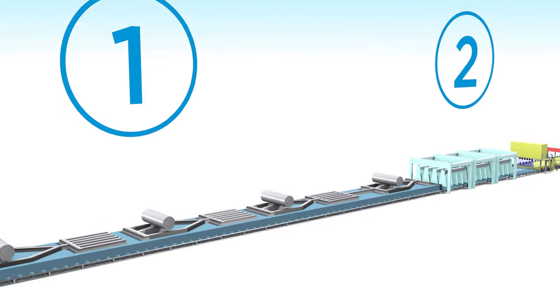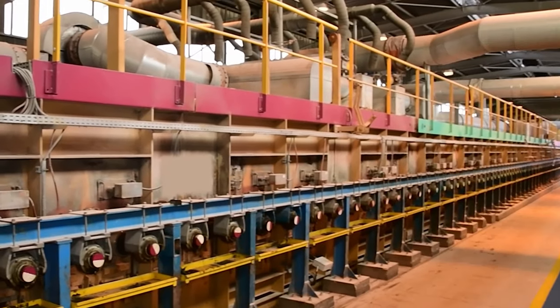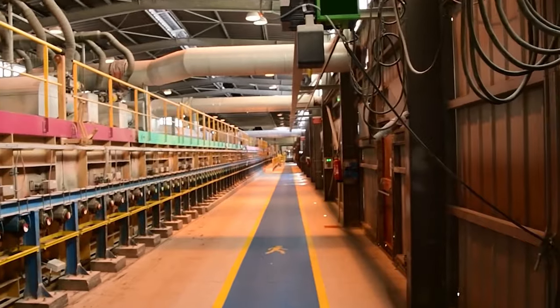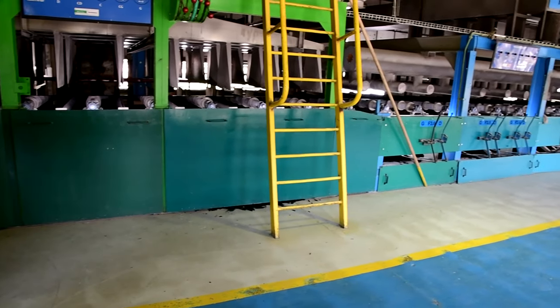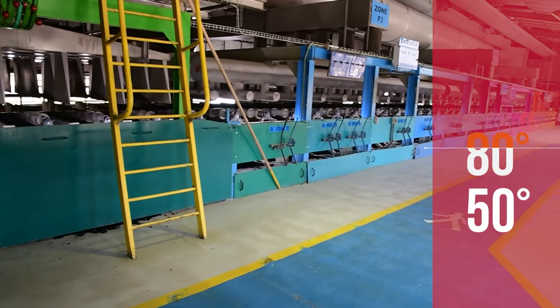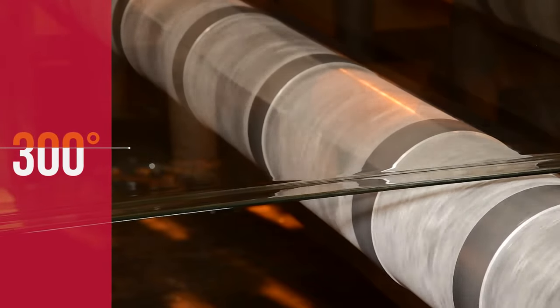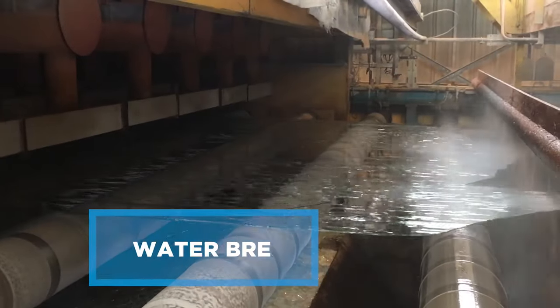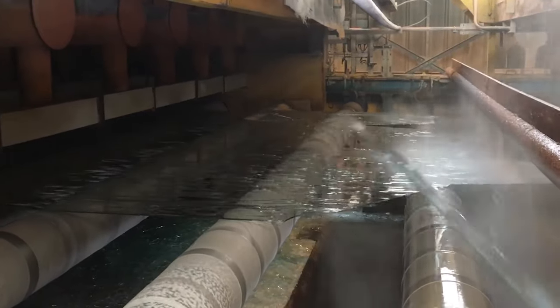The first part is the annealing zone, where the temperature decreases from 600 to 480 degrees Celsius and where permanent stress is fixed. This is a critical part of the process to give the glass a cutting quality that matches customers' requirements. The second part is the cooling zone, where, depending on its thickness, the ribbon is gradually cooled to reach a temperature between 50 and 80 degrees Celsius. At about 300 degrees Celsius, it becomes possible to lock out the downstream area of the line without impacting its upstream part — useful for maintenance purposes. This operation, called the water break, consists in sprinkling water on the surface of the ribbon to create a thermal shock that causes the glass to crack and break.